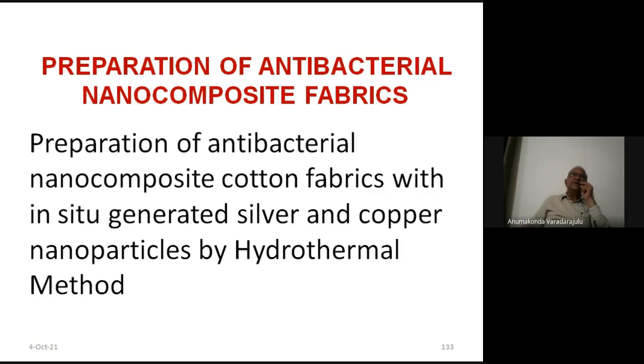But at room temperature, it takes a long time because there are not sufficient reducing groups, as in the case of the leaf extract in the films. The earlier experiments were carried out at room temperature only. That is why it took 24 hours. But here we want to hasten up the process. So by exploiting the reducing groups that are present in the fabric itself, the hydroxyl groups, we carried out this experiment at an elevated temperature of 80 degrees Celsius.